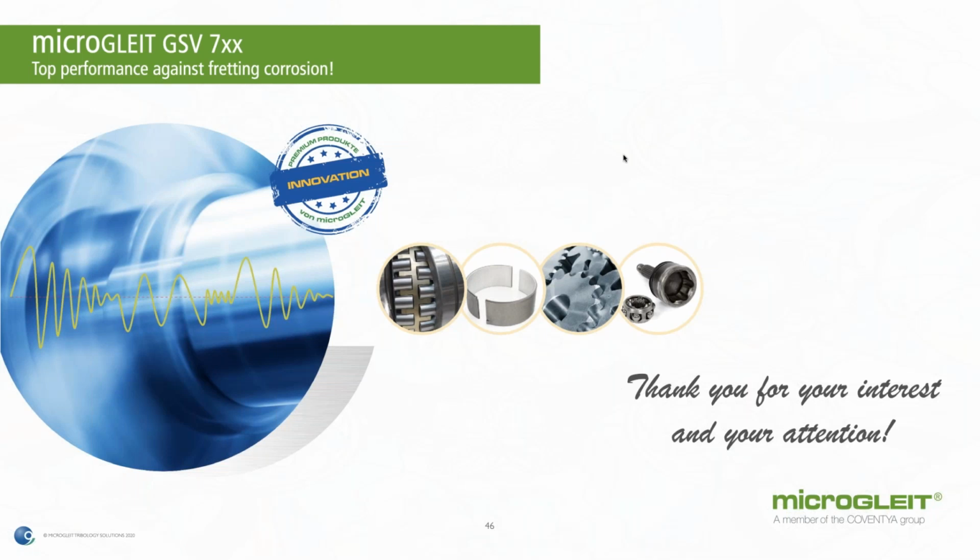Franz, do you have something to add to this? Yeah, just one sentence. When you have a phosphated screw and you use a grease paste, just take care about the coefficient of friction, because phosphating plus grease gives an even higher lubrication level. So the coefficient of friction may go down and reach a limit which you don't like. Therefore, just check up front, but basically no problem. You can use any grease or paste with phosphated surfaces, but take care about the coefficient of friction.